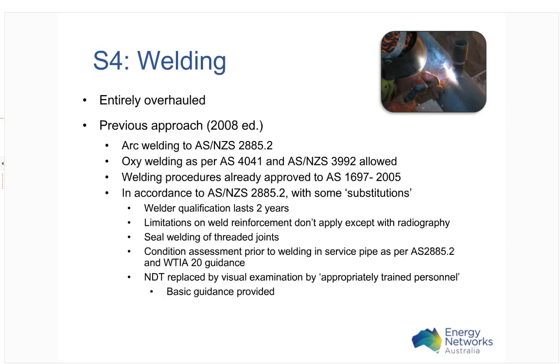That permitted arc welding practices to AS/NZS 2885.2, a very conservative approach. Oxy welding was permitted as per AS4041 and ASNZS3992. It also permitted welding procedures already approved to the previous AS1697 2005 edition. And in accordance to the reference to 2885.2, it came with a few substitutions where welder qualification lasted a period of 2 years rather than 1. Limitations on weld reinforcement didn't apply except where radiography was applied. Seal welding of threaded joints was permitted. Condition assessment prior to welding in-service pipe was as per AS2885.2 and WTIA 20 guidance, but it had NDT replaced by visual examination by appropriately trained personnel, and some basic guidance was provided in that area.